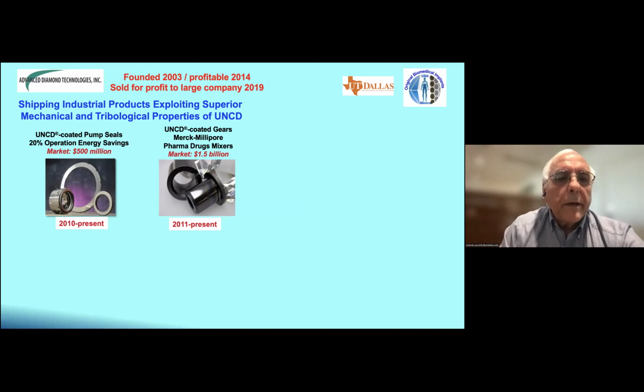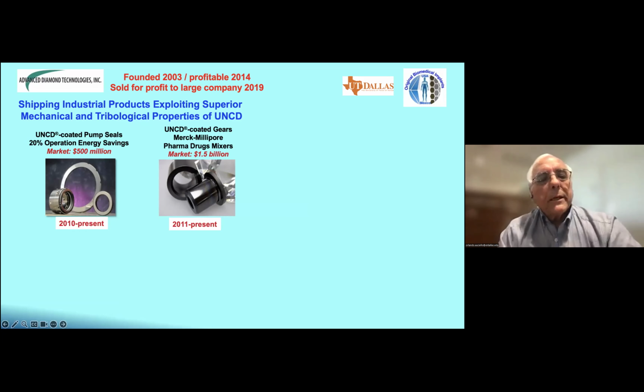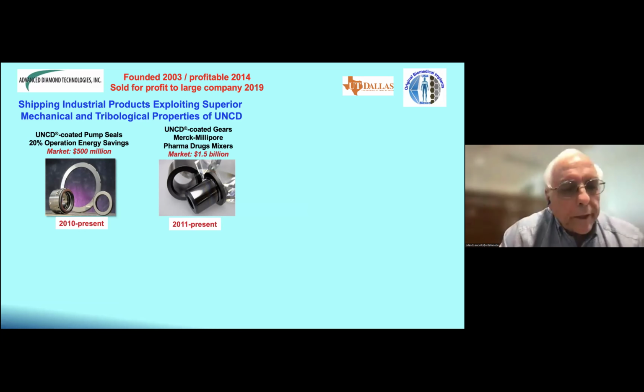So, devices that we put in the market with ADT, the first one, UNCD coated mechanical pump seals. Most mechanical pump seals in the world are silicon carbide seals with a friction coefficient of 0.5, and they have to be replaced in 4 or 5 years. With the UNCD coating, people now save up to 20% in the cost of energy of running the pump because of the 0.02 friction coefficient, and they don't wear. So you can have UNCD coated silicon carbide seals on a pump for a long time.